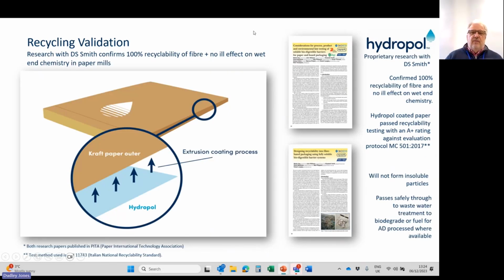As I said, our recycle validation study was conducted with DS Smith. We confirm 100% recyclability of fiber and no ill effects on wet end chemistry and paper mills. These are published papers. I can give you access to all of these. If anybody needs this, please at the end just ask. I can send you all of the materials with confirmation around biodegradability, compostability, marine safe, recycle studies, etc. But basically, you can see Hydropol coated paper passed recyclability with an A rating against the evaluation protocol MC 501:2017.